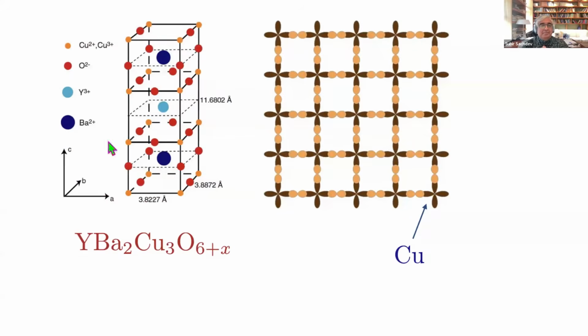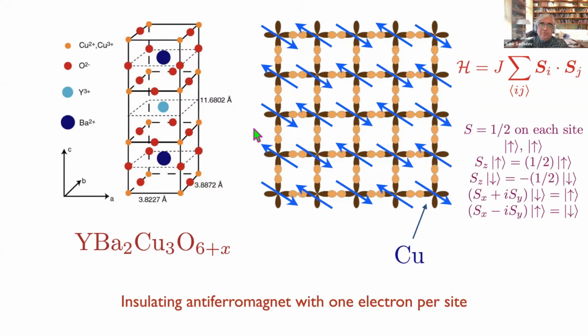The material is rather complicated, but for almost everything I'll talk about, you just need to focus on the copper atoms, which form a beautiful square lattice. Even more simply, there's only one orbital on each copper that's active. So you just need to think about a simple model on the square lattice where you can have 0, 1, or 2 electrons on each site. Now there's a parent insulator at a certain density of oxygen where you have exactly 1 electron per site. These electrons have antiferromagnetic exchange interactions. So J is positive and quite large. That's what's special about the cuprates. J is 1600 Kelvin or even higher.